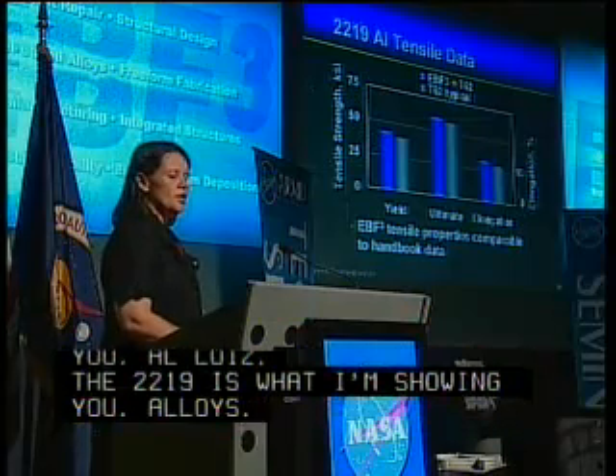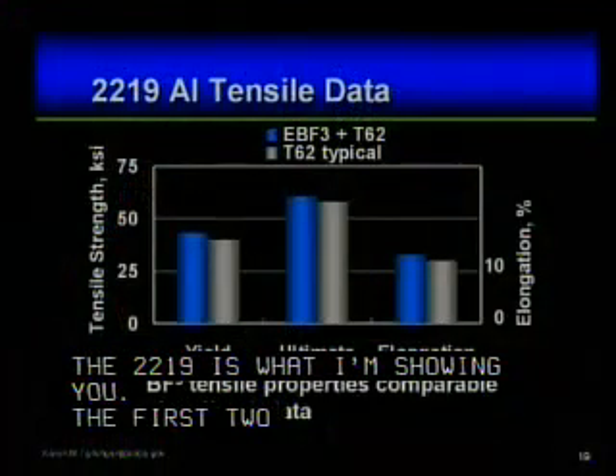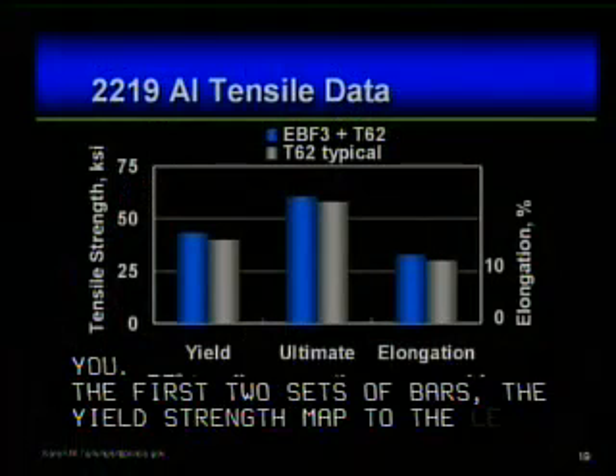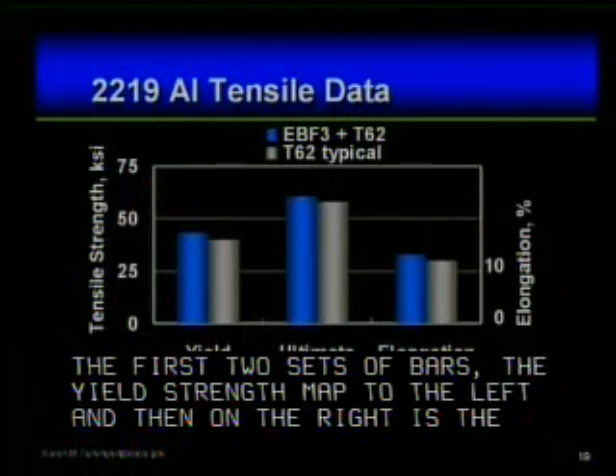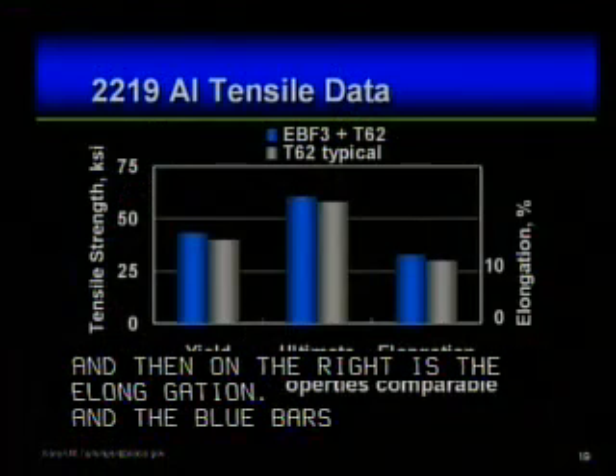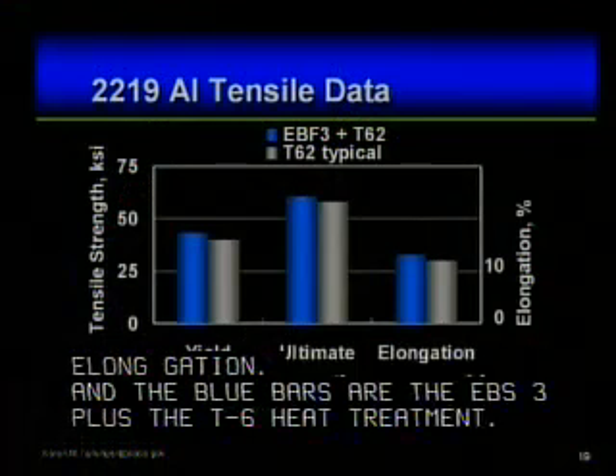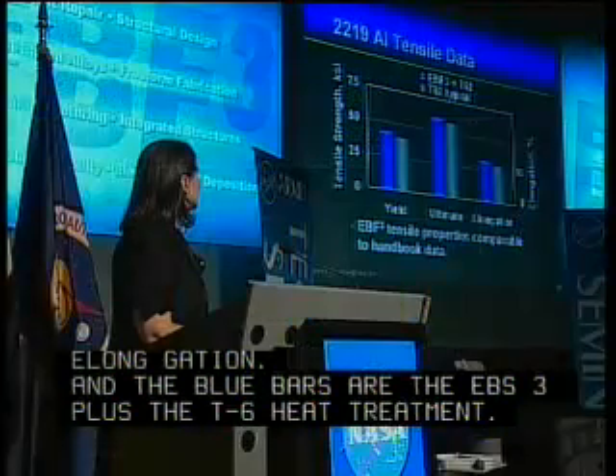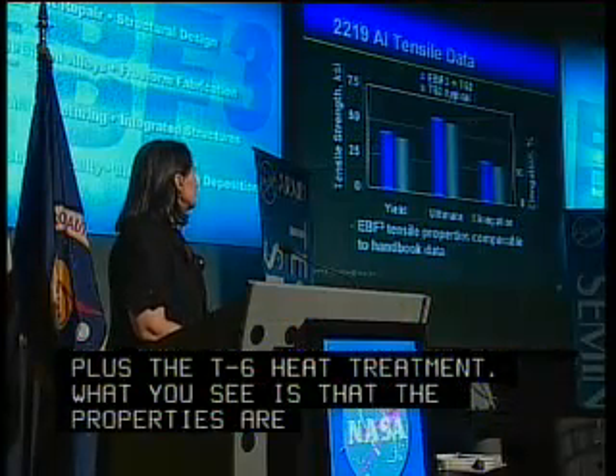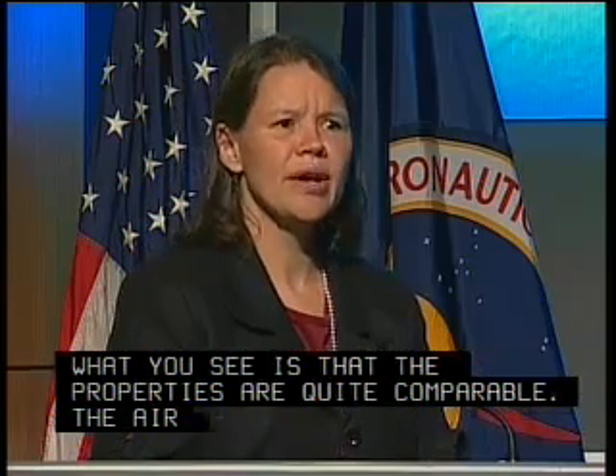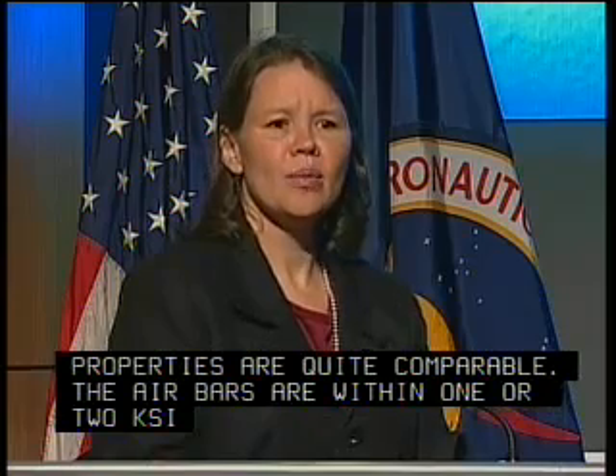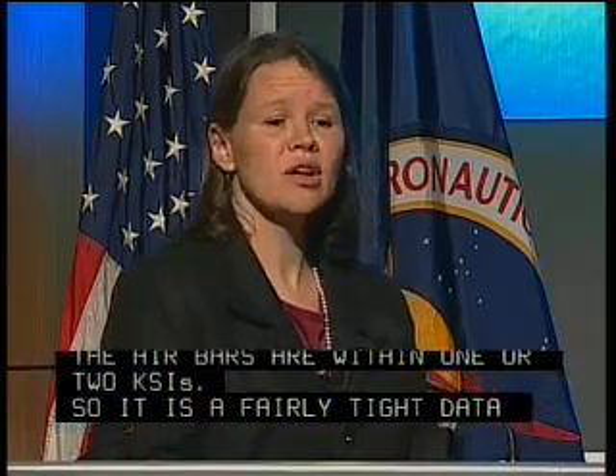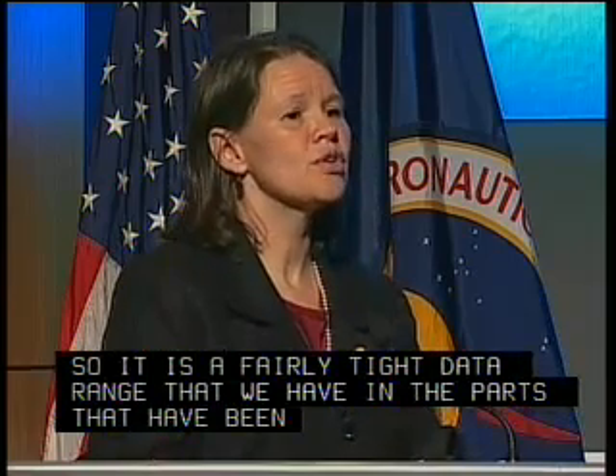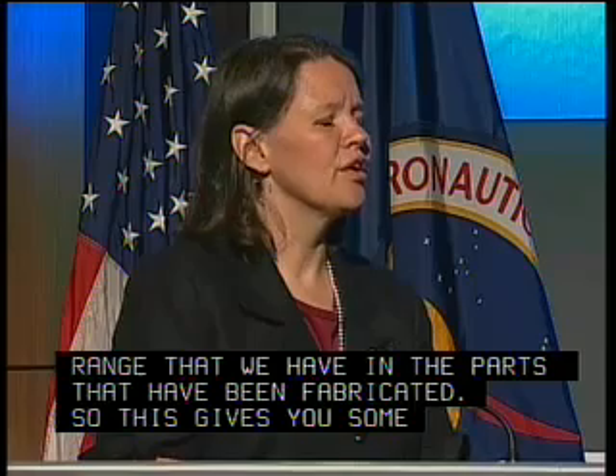so the first two sets of bars, the yield strength and the ultimate strength, map to the left, and then on the right is the elongation, so that third set of bars is the elongation. And the blue bars are the EBF³ plus the T6 heat treatment, as I showed you in the microstructure on the previous chart. And then the gray bars are handbook typical values for the same heat treatment. And what you see is that the properties are really quite comparable. I don't have error bars shown on the chart here, but the error bars are within 1 or 2 KSI. So it's a fairly tight data range that we have in the EBF³ parts that have been fabricated. So this gives us some confidence that although the microstructure may look a little bit different, mechanical properties are still performing as you would expect in a conventional material.